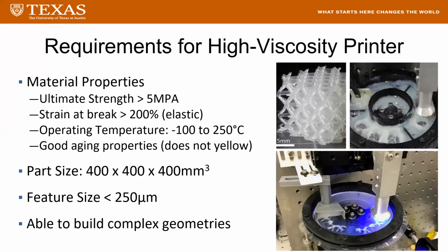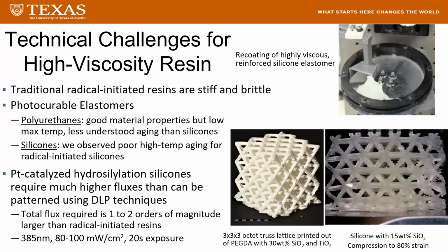This is building off of prior work that we did at Lawrence Livermore, printing UV curable silicones, which you can see at right. Our material choice stems from the tendency for traditional radical initiated polymers to be stiff and brittle when cured. More recently, there's been work into SLA printing with elastomers such as polyurethanes, which do have the material properties we desire, but silicones tend to operate at higher temperatures and also have better understood aging behavior, which has led to their widespread adoption in industrial uses.